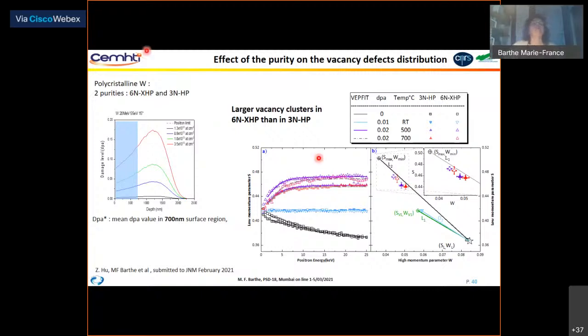We irradiated two types of samples, that means ultra high purity 6N and high purity 3N polycrystalline tungsten, using 20 MeV ions with a fluence corresponding to a damage dose of 0.02 dpa at the maximum, and the temperature was changed from room temperature to 500 and 700 degrees C. And you can see here the S parameter as a function of the energy for the virgin sample, the sample irradiated at room temperature, and the ones irradiated at 500 and 700.